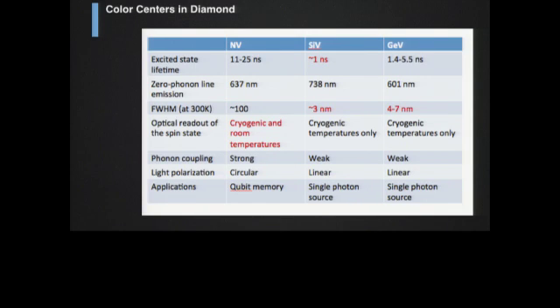It appears that the nitrogen vacancy is more of a candidate for room temperature as well as cryogenic temperature qubit kind of memory, whereas the silicon and germanium are more apt for single photon sources at these two respective wavelengths. The full width at half max is very, very sharp, 3 nanometers.